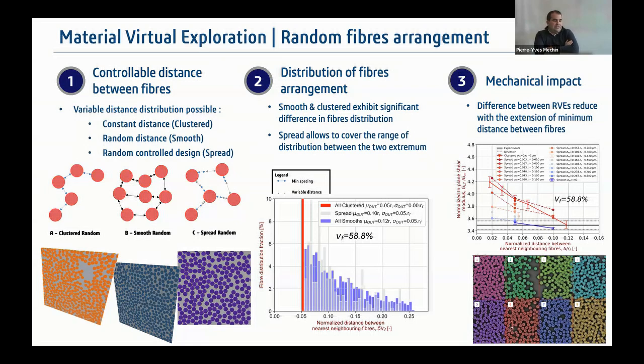And our idea is this: we were able to retrieve the variability of the picture at the bottom right, where we see that they have some resin-rich areas and control of the distance between first neighbors. And interestingly, this is really something we can do with the material virtual exploration, and retrieve the variability of the composite, in that case composite strengths, for such complex microstructures. And we see that the random fiber arrangement is pretty impactful on transverse properties and shear properties.